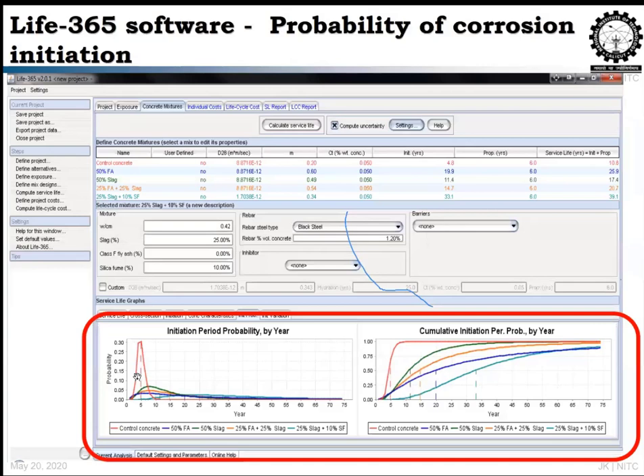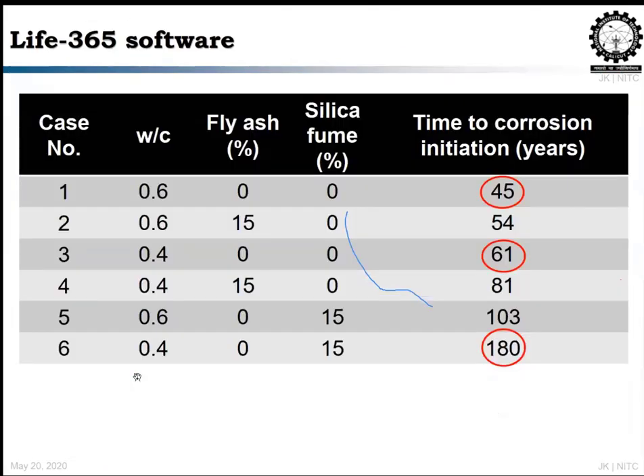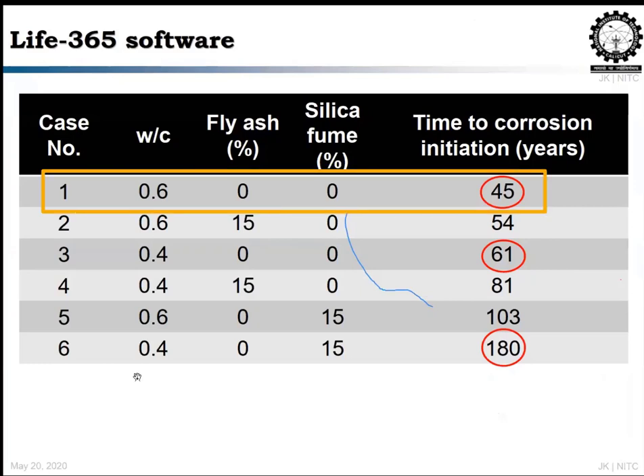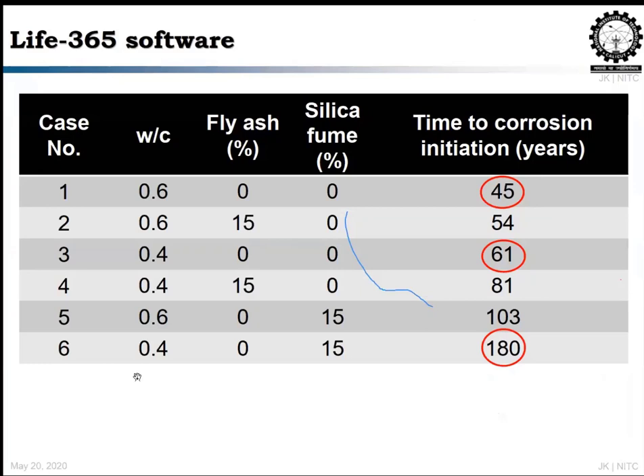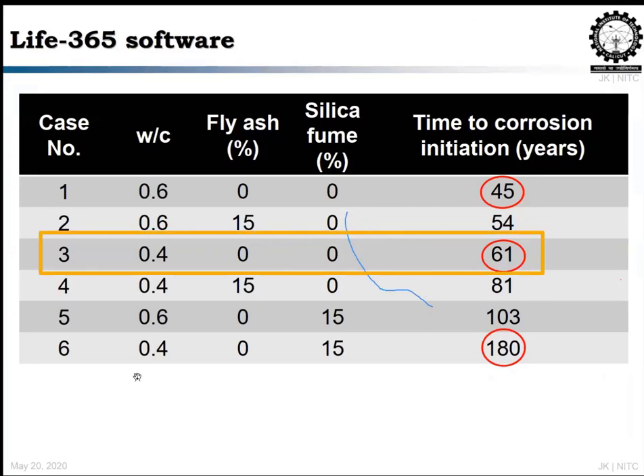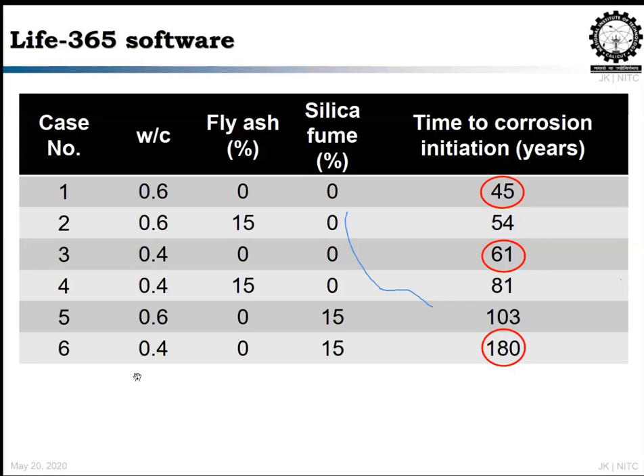I'll be putting in my inputs, and I'll tell you how much time it will take for the corrosion initiation to happen. If you see the case with a high water cement ratio of 0.6 and no fly ash or silica fume, corrosion is expected to initiate in 45 years. But case 3, which has only 0.4 water cement ratio and no SCM, has 61 years. It means 16 years more before corrosion initiation.